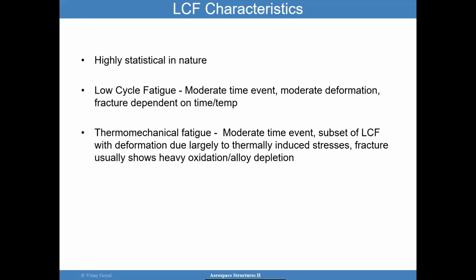The low cycle fatigue tends to be highly statistical in nature too. You have a lot of scatter in the data. You get moderate deformation. You can get a fracture dependent behavior depending upon time and temperature. So low cycle fatigue does depend on that. Thermomechanical fatigue becomes important when you have thermally induced stresses, and the fracture surfaces can also be affected by oxidation and alloy depletion.